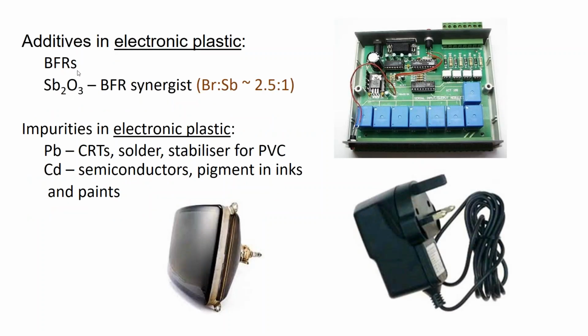Well, clearly the bromine is from brominated flame retardants. The antimony is this synergist, the ratio 2.5 or 3 to 1. But we find that in electronic waste, if it's reprocessed and recycled, you end up contaminating it with lead and cadmium, because the lead and cadmium is, if you like, in the cullet, it's in the recyclate. So cathode ray tubes, solder joints, stabilizers all contain lead. Cadmium is found in pigments and semiconductors. And if your sorting of material is imperfect, you're not sorting the plastic completely from metal, other components as well, you are bound to contaminate your plastic with things like lead and cadmium. So discrete or very notable traits of electronic plastic waste are flame retardants or bromine, antimony, and then heterogeneous concentrations of and occurrences of cadmium and lead.